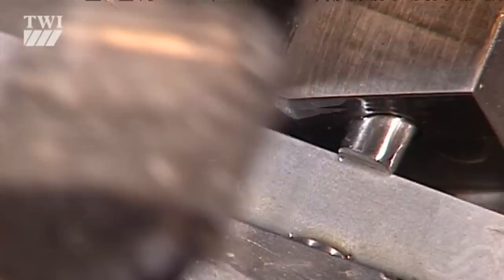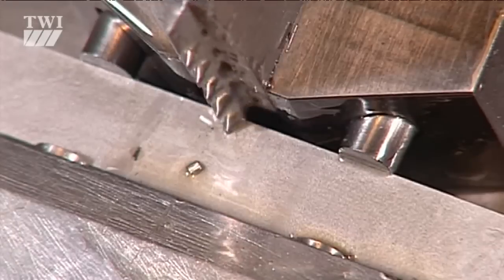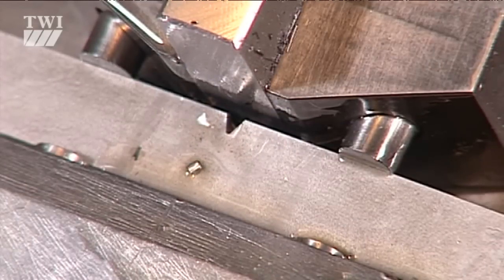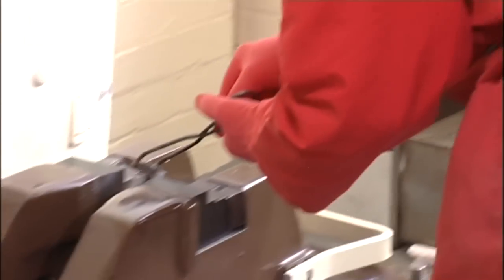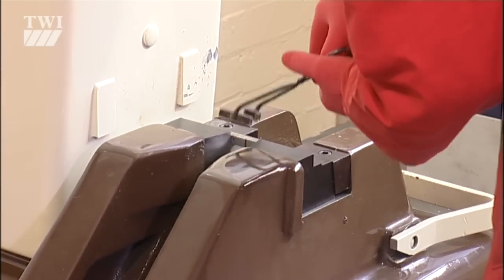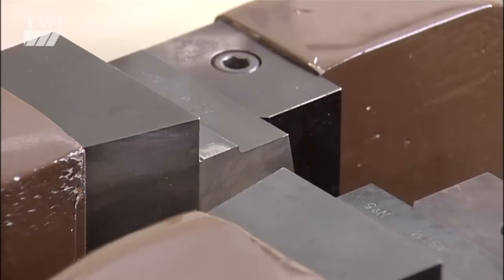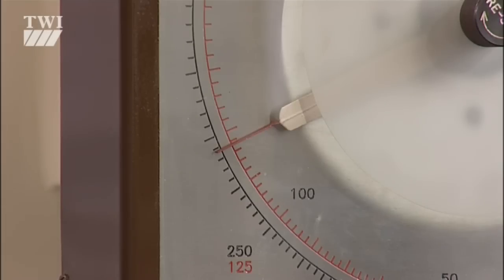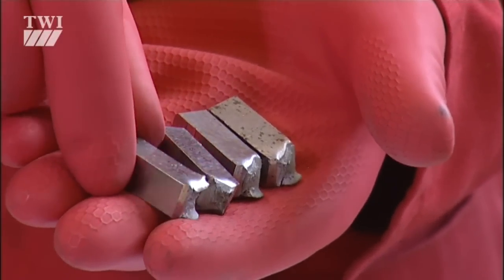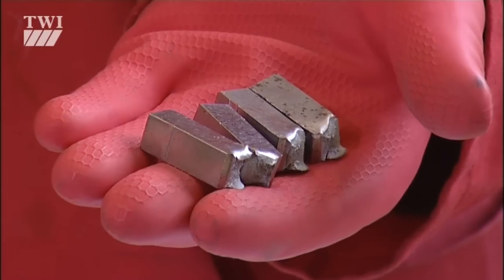Only a little material is required for each specimen. They're 55mm long, 10mm square, and have a 2mm deep notch, but can be smaller for thin materials. The specimen is struck on the opposite face to the notch. It's fractured, and the pendulum swings through by a specific amount, giving a measure of the energy required to break the material. The amount of energy absorbed in fracturing the piece gives an indication of the notch toughness of the test material.